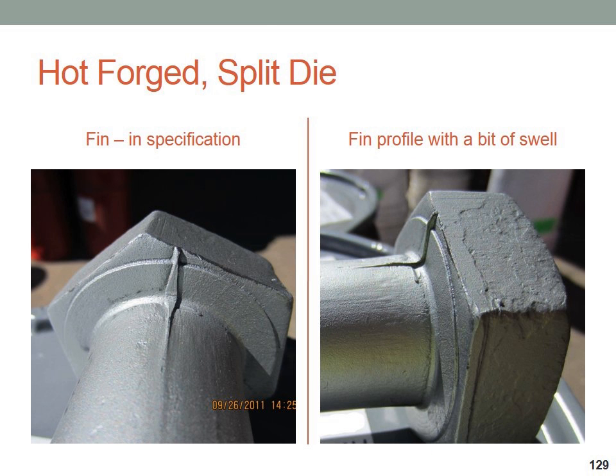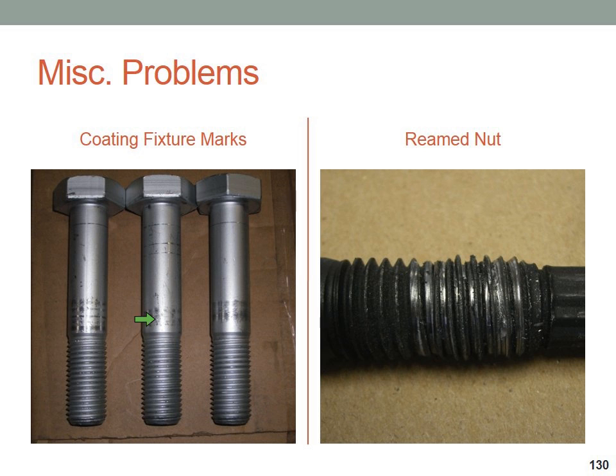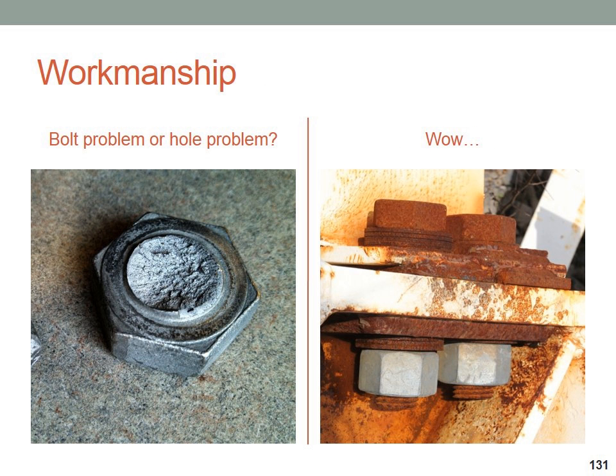And other things you might see: tool marks on hot form bolts, for example, perfectly acceptable, perfectly compliant with the standards. Burnishing marks or fixture marks. Sometimes we get thread stripping as a result of reamed nuts in the tapping operation. We're seeing more and more people that for whatever reason are installing bolts from the head side, and sometimes they are completely twisting off the bolt heads, again because of the bearing or the friction in the hole on the body of the bolt. And once in a while we see something like this, which is just hard to explain. That got through so many levels of engineering and QC and ended up like that.